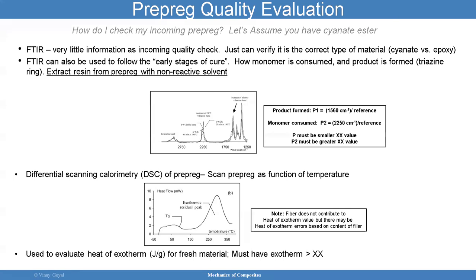transform process. You also have DSC, like I said, and you can then scan the prepreg as a function of temperature. And by doing that, you can then determine the delta H, as I discussed before, and that's gonna give us a lot of clues about whether the degree of cure has been compromised or not. Note, I wanna make sure you understand the fiber does not contribute to the heat of exotherm value, but it could influence errors, right, based on the content of the filler.